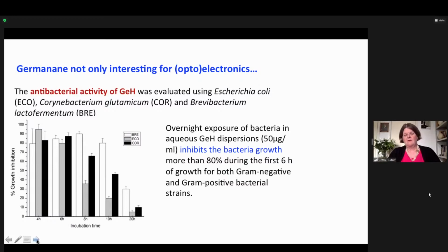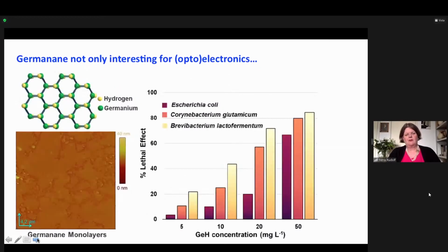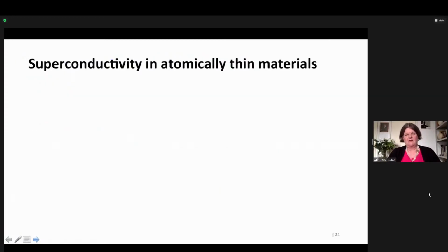And that is a very positive thing because the germanane is not something which is particularly difficult to prepare. And one can also make the monolayers and see that, depending on the concentration in solution, one can also kill both types of bacteria very efficiently. So it's not only good for optoelectronics, as people might think, but there are also other exciting properties, and we are just at the beginning of discovering it.